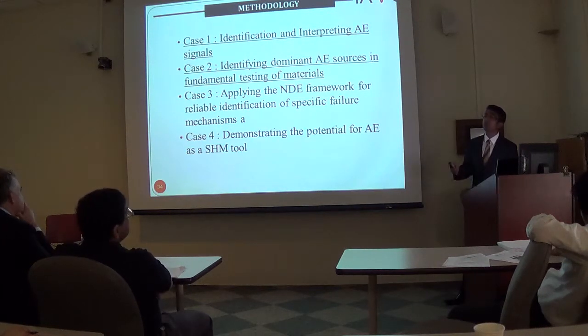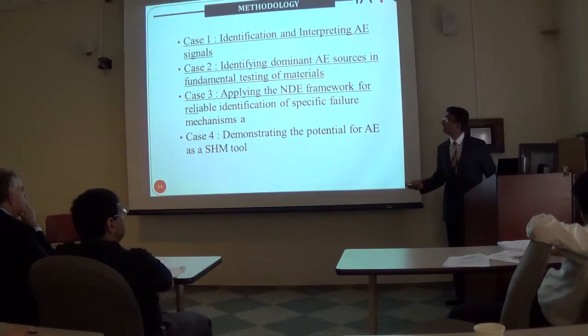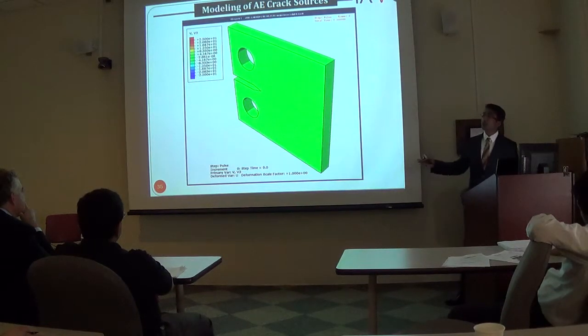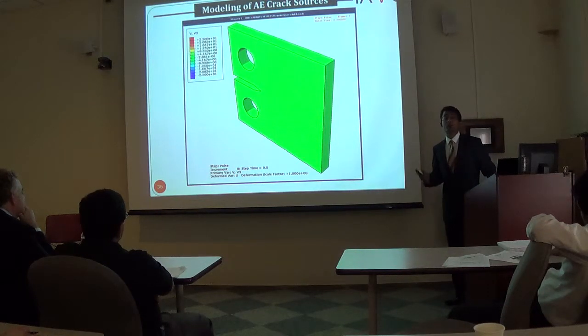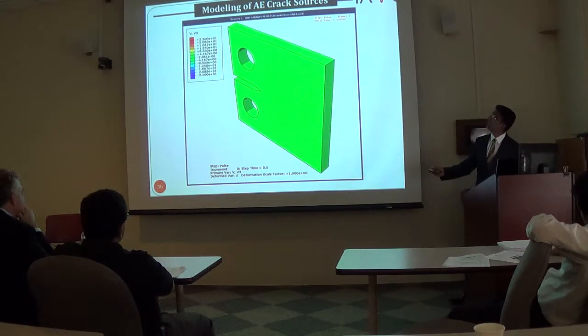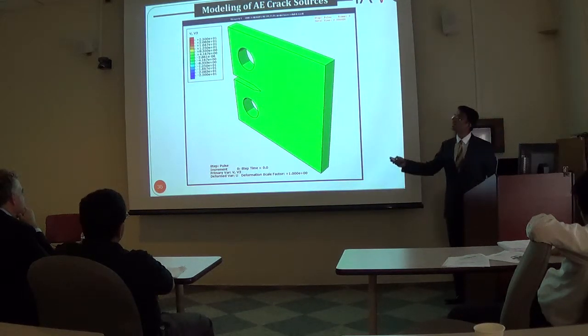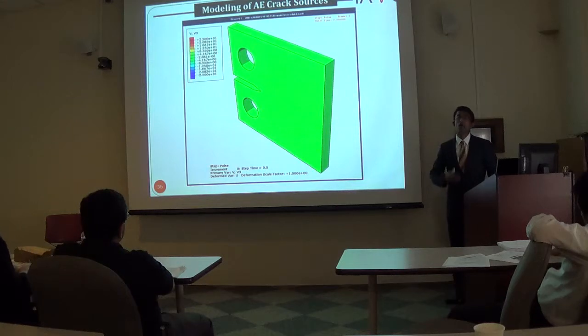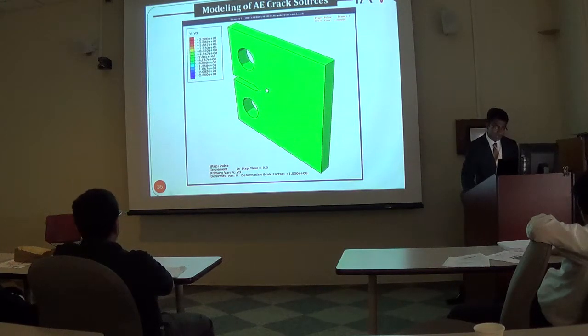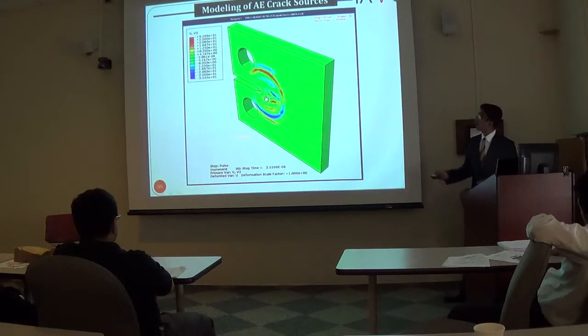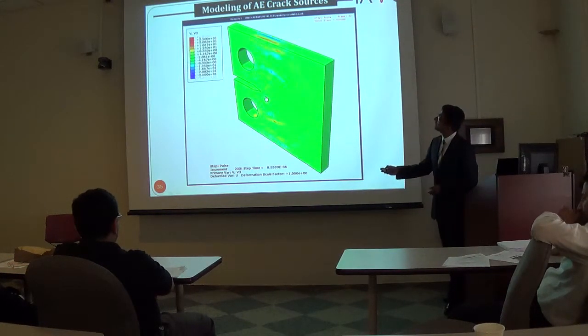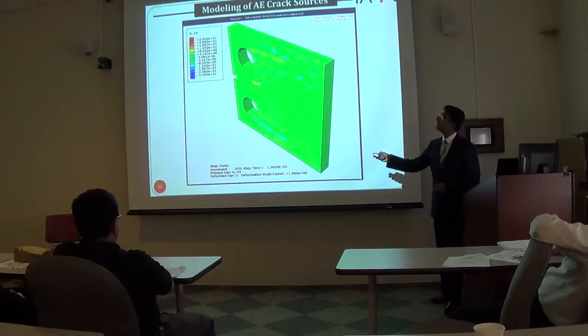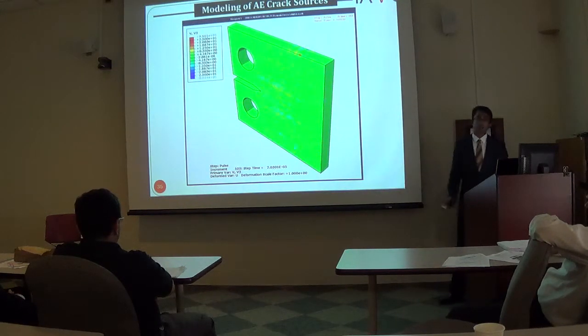For that purpose, compact tension specimens were designed and were experimentally tested. But prior to actually experimentally testing the compact tension specimens, acoustic emissions were modeled using finite element analysis to see how the acoustic emissions are produced due to the crack initiation and how they interact with the structural features and how it affects the actual wave phenomenon itself. So if I can go ahead and play the video, you can see how the acoustic emissions are produced as the crack goes through the material and how it gets affected as it hits or interacts with structural geometries and the boundaries.